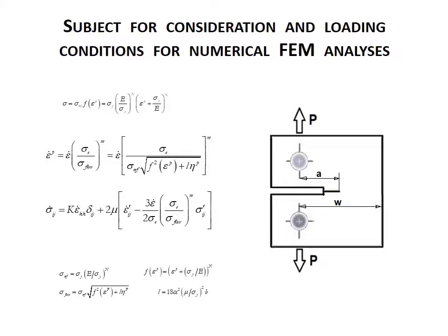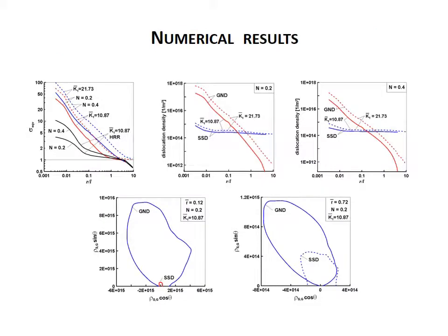In the numerical results to be considered, the comparative reanalysis is based on assuming different values of remotely applied elastic stress intensity factor. The material constitutive equation is implemented in ANSYS software by user subroutine, and the crack-tip fields are evaluated with novel parameters in the form of the intrinsic material length, characterizing the scale over which gradient effects become significant.